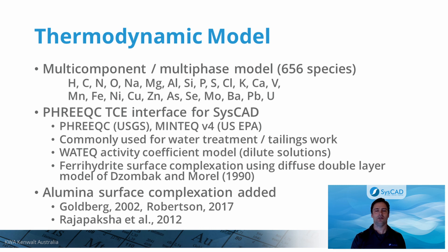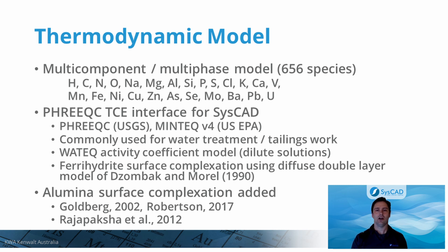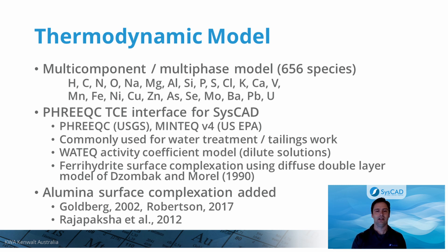The PHREEQC water treatment model used in this analysis includes 656 species and nearly 30 elements. It is based upon the MINTEQ version 4 database developed by the US EPA. PHREEQC is developed and maintained by the USGS. This package was selected because it contains commonly used water treatment tailings environmental type data. The model uses the WATEQ4 activity coefficient model which is suitable for this application. Ferrihydrite and alumina surface complexation is also considered. This model is very comprehensive and allows for simulation of typical mine water treatment processes.